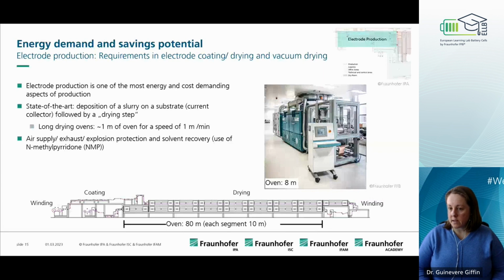So if you look at the graph on the right, this is a small pilot facility that is part of the Fraunhofer FFB. And here you can see they have about 8 meters of drying space. This is the blue section or greenish blue section in the middle. However, in an industrial scale drying facility, you're really looking at about 80 to 100 meters of drying. And so therefore, this is 10 times as long, but would enable a production speed of 80 to 100 meters per minute. So you can imagine the energy consumption for this is extremely high because you need the air supply for the drying, the exhaust, and of course you need the explosion protection and solvent recovery units due to the use of NMP as a solvent for the cathode production.